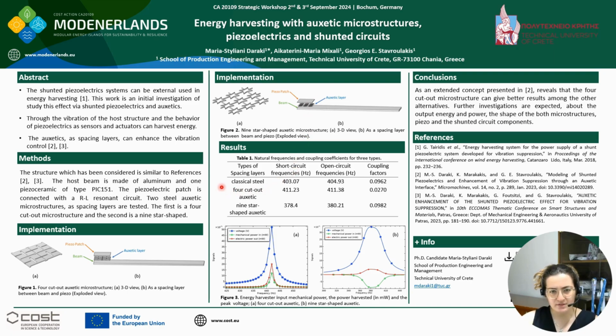From this first investigation, three types of spacing layers are compared: a classical steel layer and the two auxetic microstructures. It is shown that the 9-star shape microstructure gives a higher value of coupling factor.